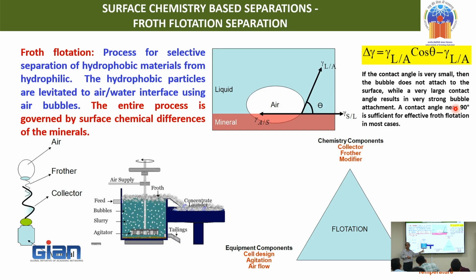Agitation speed is important because I told you the interaction of the frother to the collector is by very weak van der Waals forces. Even here, everything is happening only for a few minutes; it is not kept for a longer time so that the complete interaction takes place. You are not allowing for that. Kinetics is very important. Therefore, we are allowing the entire process to happen in 5, 10, 15 minutes. So whatever little linkages are there at each place, they remain intact. They don't get disturbed by the shear which is happening, because there is vigorous agitation. Because of this vigorous agitation, whatever has got attached should not get detached. Therefore, the agitation is very important.